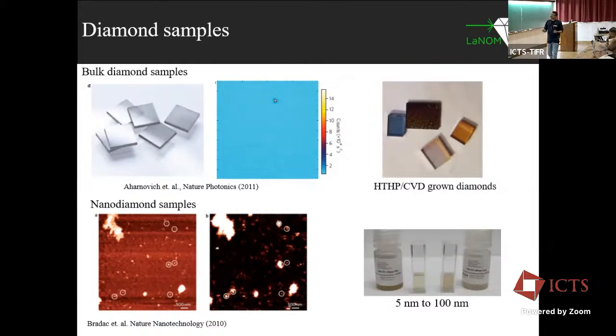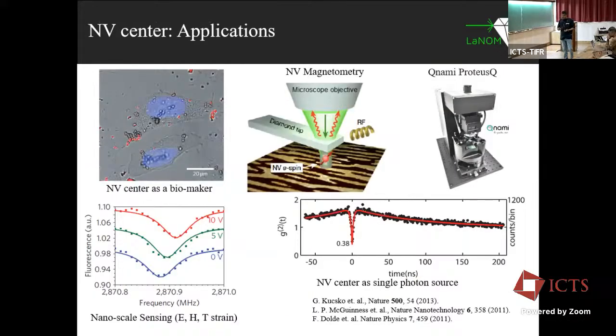One can also buy nanodiamond samples, which are like colloidal particles with sizes from 5 to 100 nanometers, which can also have NV centers. The NV center is a very stable system, it does not have photoblinking or photobleaching, so we can integrate it for many biological applications where these nanodiamonds are quite interesting. And since the sizes are very small, they can be very easily integrated into photonic structures, unlike making a photonic structure in diamond itself. As mentioned in the last talk, it is an excellent fluorescent biomarker because there is no photobleaching.